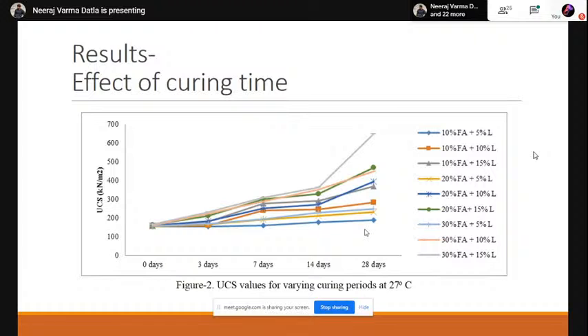This is due to the polycondensation which we have discussed earlier, which needs some time to get a well-developed network. So with increase in the liquid activator content, so with increase in the alkaline content, more silica and alumina get dissolved, so that a well-established structure is going to take place, and the strength of the soil is going to increase.